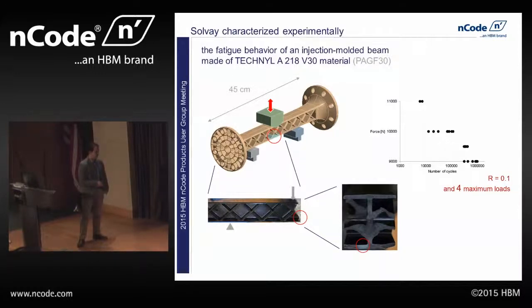And so what we see is that in most cases we have this fatigue failure happening right down here at the base of where these ribs connect at the center of the beam. And if you think about the microscopic effects that I was talking about before, it makes a little bit of sense that we would see that here, right? Because we've got these fibers that are aligned very well in the direction of the ribs, and then at this joint here we have this little ball of randomly aligned fibers where the material is not going to be as strong.